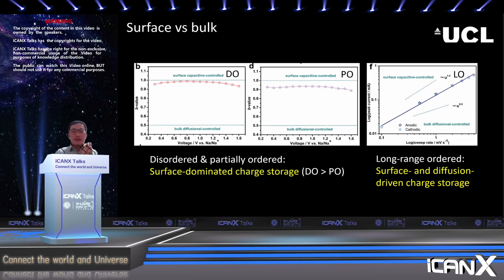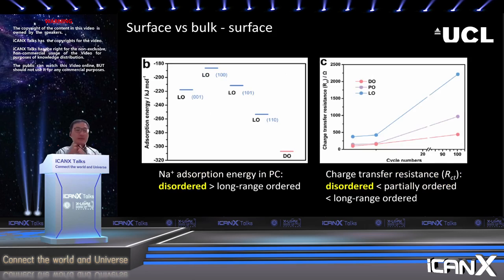Based on our observation of the surface and the bulk storage, we try to understand why this disordered material could have higher surface storage. We use simulation to estimate the adsorption energy between the sodium ions and the 001 crystal plane of titanium dioxide. What we found is that for the amorphous titanium dioxide, the sodium adsorption energy in the traditional electrolyte is much higher than the long-range ordered crystalline material.